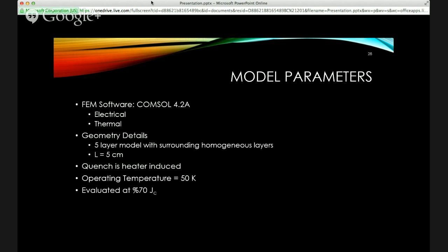And for my models, it took about 13 hours to run one. And you run multiple times so that you can duplicate what you've been doing, but also to make sure that you're getting the correct response. So in this case, in order to initiate that quench, I used a heater that I actually input into the model itself. And I operated at a 50K temperature, and I use a 70% JC. So what that means, the 70% JC, I was using an applied current that was 70% of the critical current value. Does that make sense?